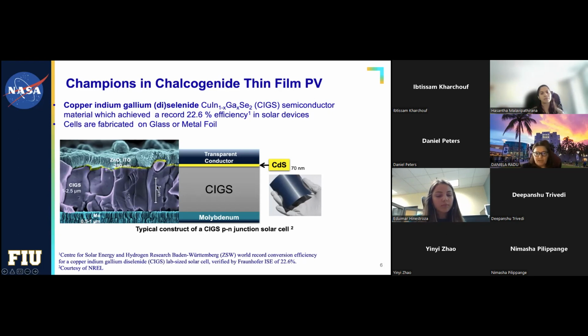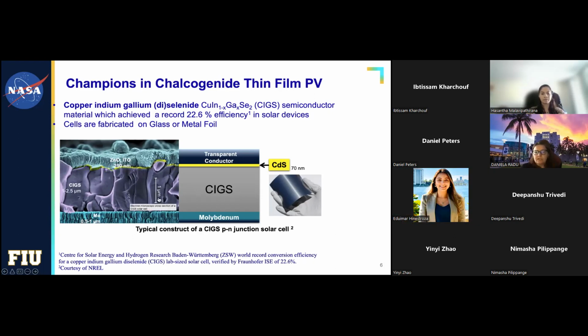And this particular cell is actually one of the previous records. Right now it's around 26%. But this is from the Fraunhofer Institute in Germany, which is a 22.6% efficiency solar cell. And you see, it is quite simplistic if you think. So you have the molybdenum, which is done by sputtering, by the way, so that's a vacuum process. And then you have the CIGS, which is deposited originally by sputtering and subjected to an annealing process, which creates these large crystals. You need the large crystals for the continuum, for the electron flow. And then you have this cadmium sulfide layer and the transparent conductor.